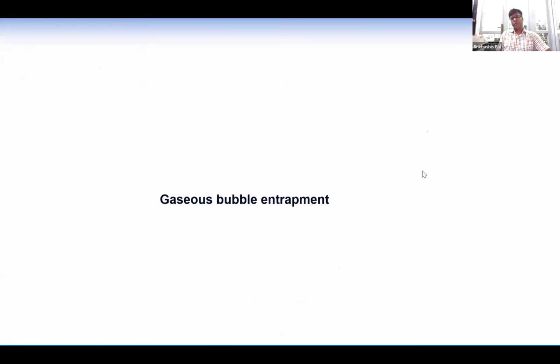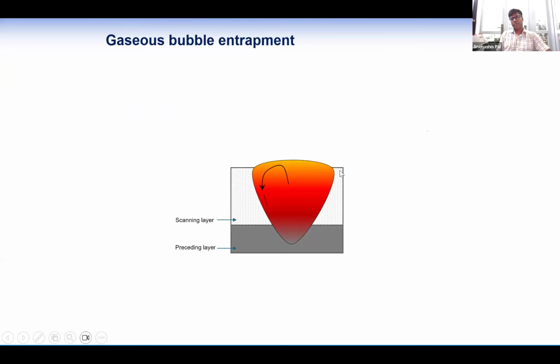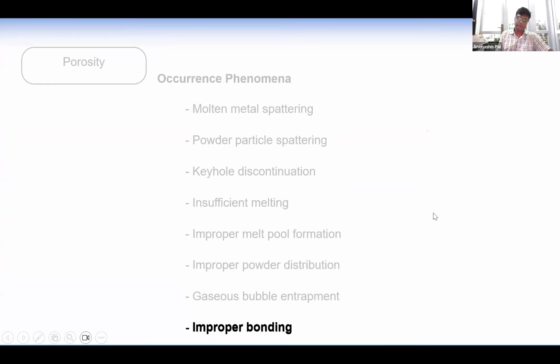Also, a gaseous bubble can create some problems during the vortex. The gaseous bubble will also move with this. It's good that it cools down from bottom to top, so the vortex will also go upwards, and also the gaseous bubble. If it stays there, then it will create a pore. But if it stays at the top, during next layer melting it will be added to the next layer, so it will not be a problem. But if it stays somewhere in the bottom place or middle place, it can stay and create some pore.